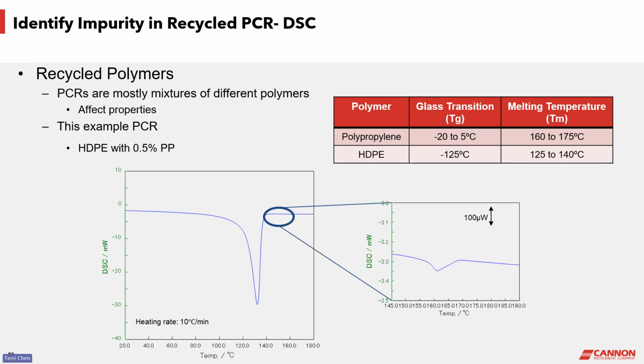However, at a temperature around 160 degrees C, we can also identify another small melting peak, which correlates to the melting of PP. So by integrating the melting enthalpy and comparing it to the melting enthalpy of a pure PP, we can get a reasonable estimation of how much PP contamination there is in this particular batch of PCR.